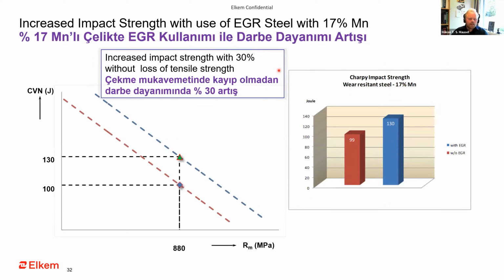And we increased the impact strength in this grade without any loss of tensile strength. So we went from 100 joules on the Charpy testing up to 130 joules. So that is quite substantial. And the tensile strength stayed at 880 megapascals.